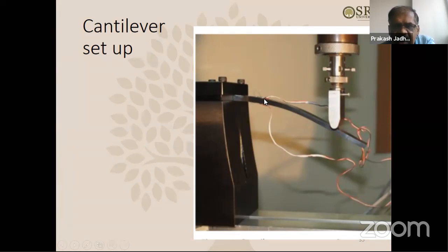And of course we are using strain gauges, and we designed some special fixture for cantilever kind of loading because we want to see the effect of these multiple ply drops near the surface. As we have seen in the earlier study, plies near the surface are very sensitive to failure. So we decided to subject this ply drop near the surface to tension or compression. This kind of setup is the best to subject them to tensile and compressive stresses. So when it bends, the bottom surface is subjected to compression and the top surface to tension, like this. And this is a special loading fixture that we designed so that we can achieve this bending.